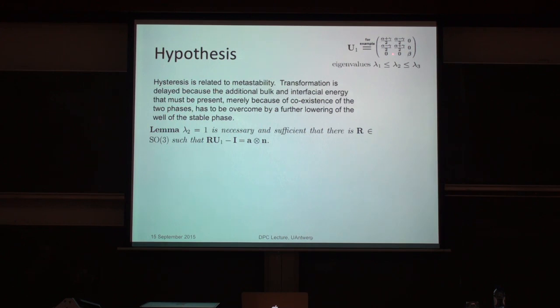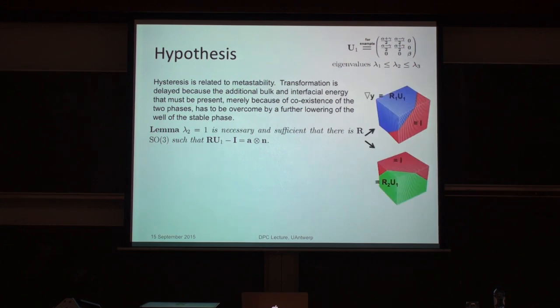You recognize, first of all, so there's that linear transformation between the phases. And remember, it has three eigenvalues, lambda 1, lambda 2, lambda 3. And you realize that there's a little mathematical lemma which says that, and don't worry about the notation, it says that if the middle eigenvalue of this matrix is 1, then the two phases are perfectly compatible. This is the compatibility equation. And again, I won't explain the details, but you can see in the pictures that if the middle eigenvalue of this matrix is 1, you can have a perfect interface.